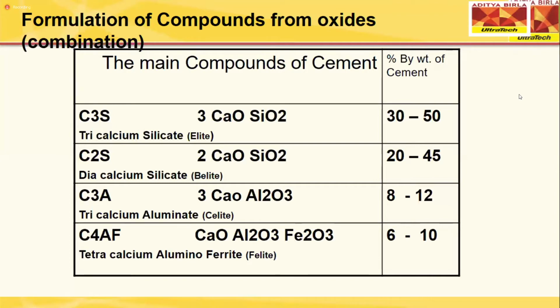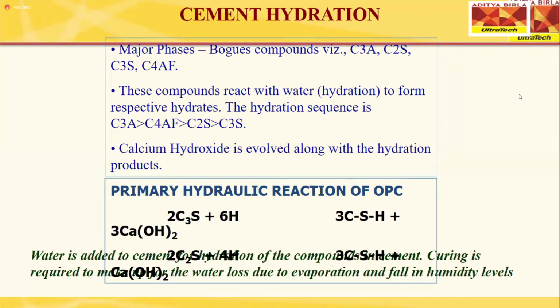Next slide, please. Yeah. So we've seen the four major phases: C3S, C2S, C3A, C4AF, and the reaction when the water is added, the hydration reaction. When the primary hydraulic reaction takes place between the products C3S and C2S, we get calcium silicate hydrate gel, which gives the binding properties in the cement and which gives a solid mass in the cement. Now, we all know that cement alone is not used. It is either mixed with sand or it is mixed with sand and aggregate. So if we mix sand and aggregate, we call it concrete. So the strength of the concrete is basically driven by the amount of calcium silicate hydrate gel produced in the system. Next.